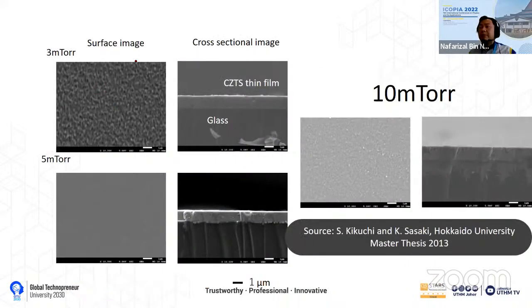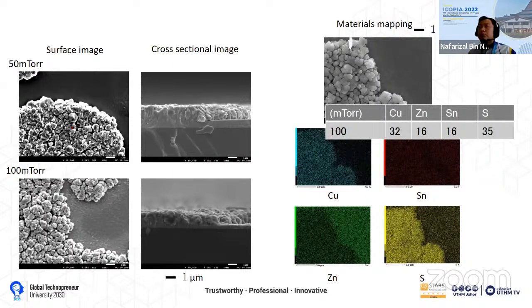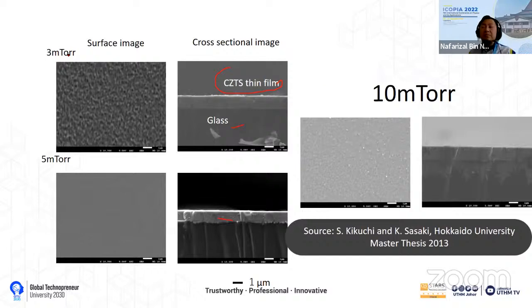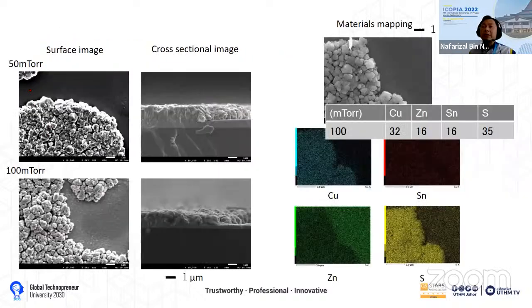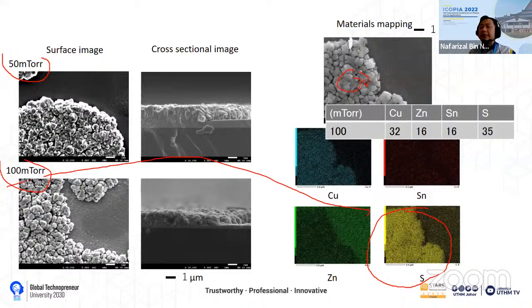So this is an example where we deposit the CZTS thin film on glass. We can see a very good uniform thin film here. And then we also see what happens when we increase the chamber pressure. This is 3 millitorr, 5 millitorr, and then we increase to 50 and 100 millitorr. We can see the surface becomes like nanoparticles on top of the smooth surface. By studying the particle morphology and chemical composition, we can see that there is a lot of sulfur in these nanoparticles. This shows that higher gas chamber pressure can contribute to more sulfur content inside the thin film.